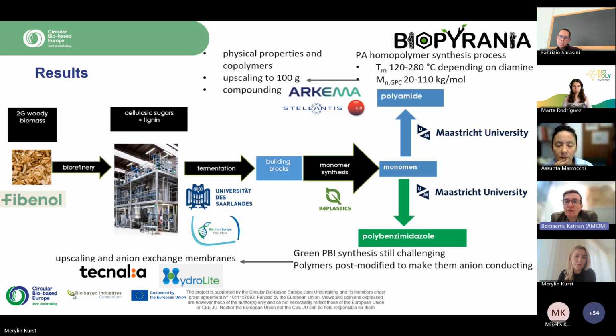For the polyamides, we developed a route to make polyamide homopolymers, and depending on the choice of the diamine, we can achieve melting points between 120 and 280 degrees centigrade, and molecular weights of 20,000 to 110,000. Physical properties of polymers and copolymers are currently under investigation, where Arkema is blending those polymers with, for example, reinforcing agents. And we are currently in the stage of scaling up the polymer to 100 gram scale.